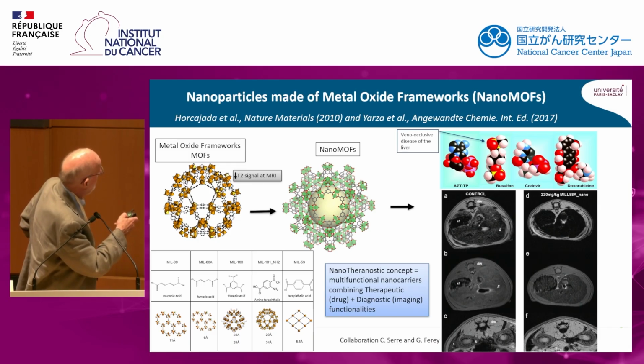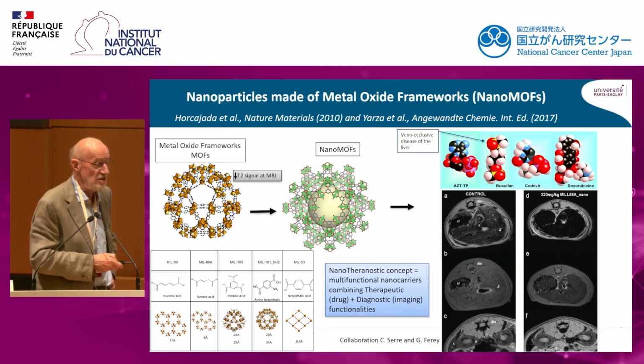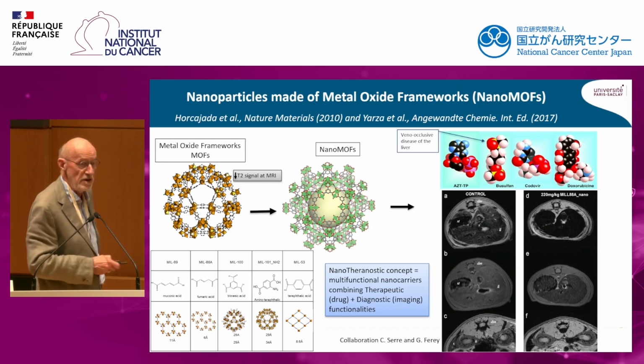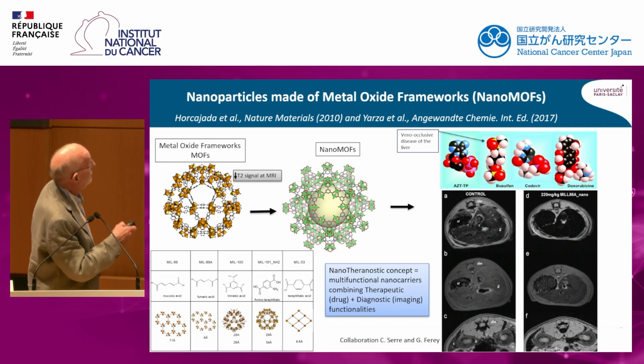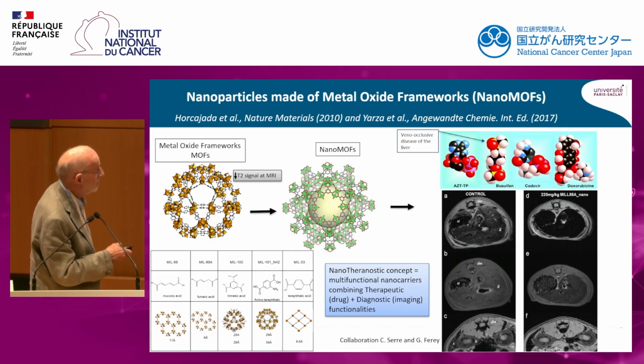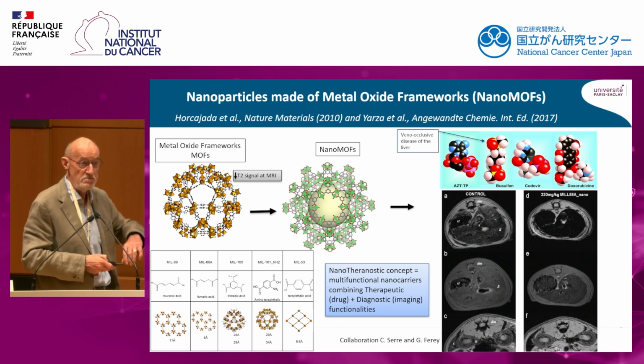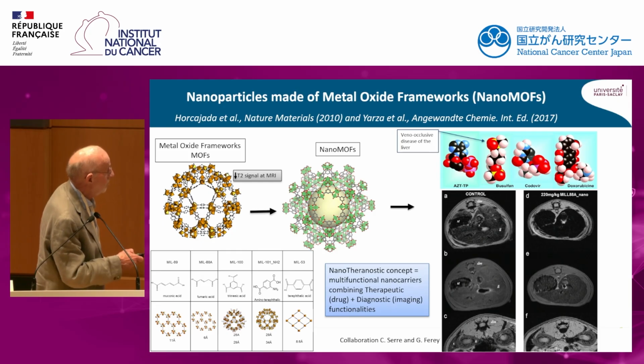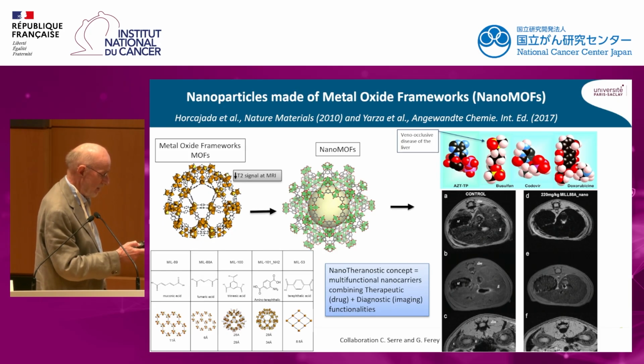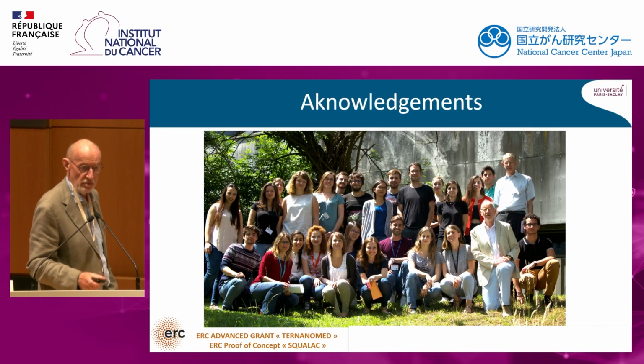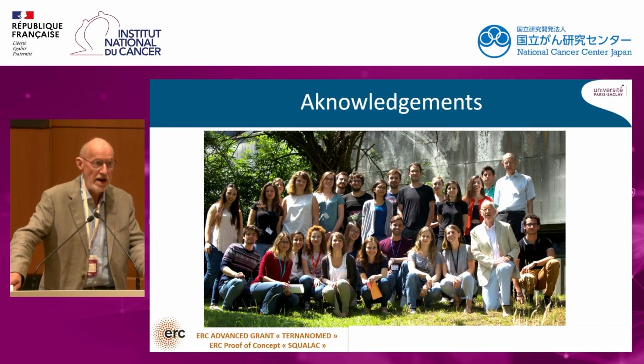And what is interesting is that the iron oxide clusters are decreasing the T2 signal at magnetic resonance imaging. So this allows you to do some imaging. And this was the concept we developed in 2010 of nanotheranostics, corresponding to multifunctional nanocarriers, which are able to combine a therapeutic functionality because you have a drug encapsulation, but also a diagnostic functionality because you are able to do imaging.